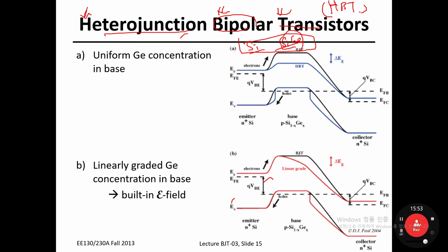So in industry, to fabricate very high-speed integrated circuit chips, HBT has been widely adopted because it is a CMOS fabrication compatible technique, and SiGe was widely adopted in planar bulk MOSFET technology about two decades ago. In 2003, Intel Corporation for the first time adopted silicon germanium material in the source and drain region for the P-type MOSFET. So silicon germanium is quite familiar, and the industry has a lot of hands-on experience. So this is not a very high barrier.